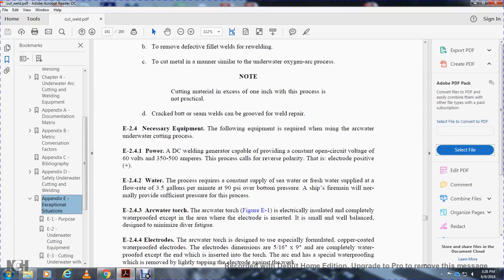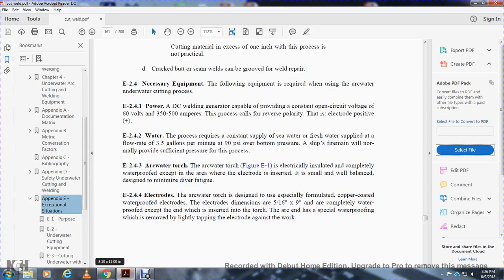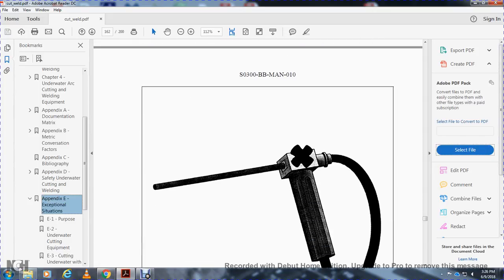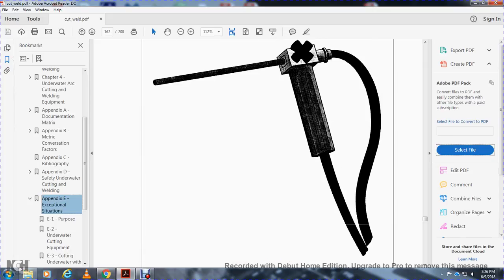E2.4.3, arc water torch. Arc water torch, figure E1, is electrically insulated and completely waterproof except for the area where the electrode is inserted, It is small and well balanced, designed to minimize diver fatigue. E2.4.4, electrodes. The arc water torch uses a specially formulated copper-coated, waterproof electrode. The electrode's dimensions are 5/16 of an inch by 9 inches. They are completely waterproof except for the end which is inserted into the torch. The arc end of the electrode is exposed by lightly tapping the electrode against the work. Alright, this shows your arc water torch assembly.